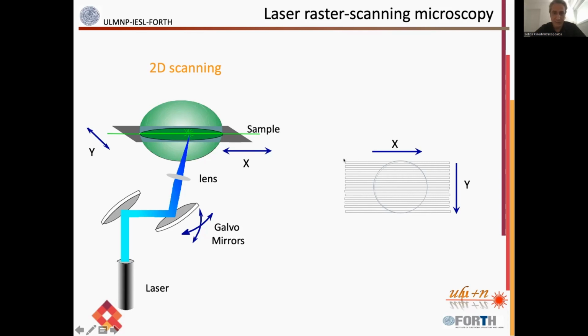So very, very fast, for every position of the beam, the detector is recording a value, and then our program reconstructs these values into a contrasted image, and is actually creating an image. This whole process is taking approximately 1 second for every frame for 500 by 500 measurements, or pixels if you like. So for a 500 by 500 pixels image, we need approximately 1 second.